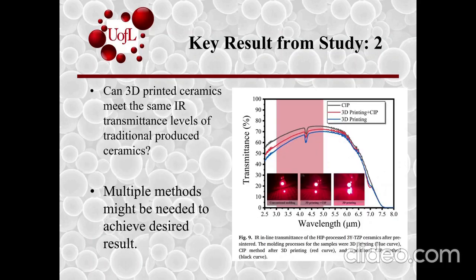Another result from this study, well, they were asking, can these ceramics meet the same IR transmittance levels of traditionally produced ceramics? And they found that through all their testing, yes, they could. But they needed to include multiple sintering methods in order to get better and better transmittance. In this graph, you can see how just by 3D printing they had a fine transmittance, but they used cold isostatic pressing to increase that transmittance. And they got around a 71% transmittance for the wavelength that they were requiring. So what I learned through this is that multiple methods might be needed to achieve a result, like they did with the multiple different sintering processes, HIP and CIP.